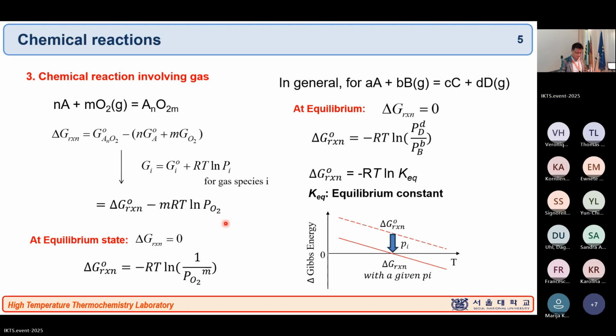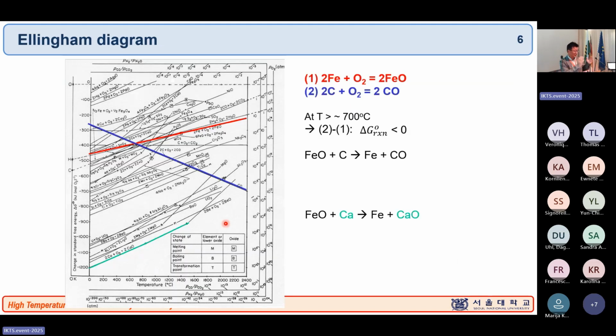So at least you understand the difference between delta G naught of reaction and delta G of reaction. And one of the most famous diagrams about the oxidation of metals is the Ellingham diagram, of course. The Ellingham diagram is a collection of all the standard Gibbs energies of reaction for a metal with 1 mole of oxygen becoming a metal oxide. That's the collection of the Gibbs energy here.